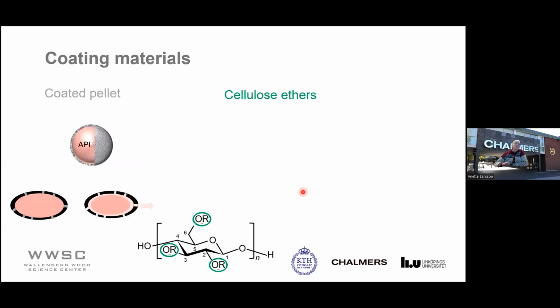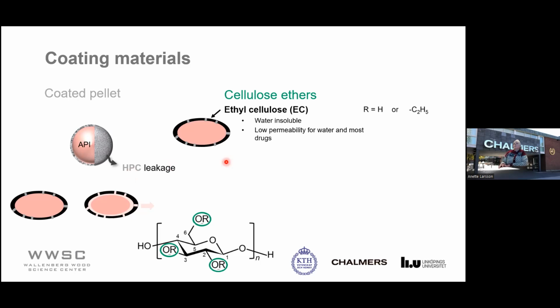So I will now illustrate this on this system here, where we have the pore forming agent that then leaks out. In this case, I will illustrate it with HPC. So we have 2 different cellulose ethers here. The first one is ethyl groups. This means that we have ethyl groups placed on the substituents here. And this pharmaceutically approved polymer, ethyl cellulose, has a degree of substitution that is around 2.5. And that means that on average, 2.5 of these groups per glucose unit are substituted.